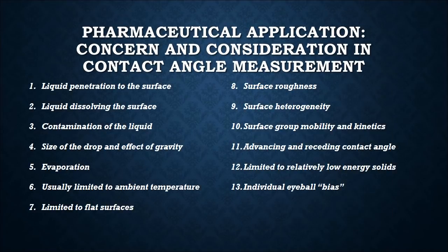So here we list the concerns and considerations of contact angle measurement. We need to consider whether the liquid penetrates into the surface, whether the liquid dissolves the surface of a solid, whether there is contamination of the liquid that can actually interact with the surface, and the size of the drop and the effect of gravity and evaporation.